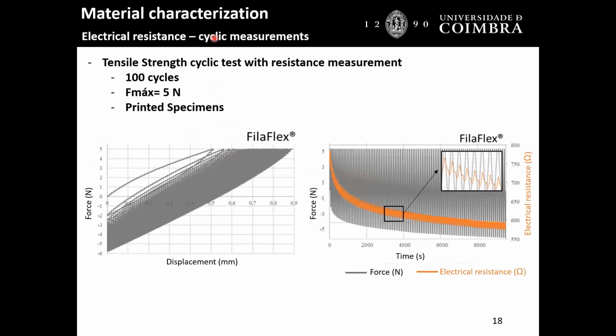And then we made, in the elastic deformation region, cyclic measurements, okay? With a maximum force of 5 newtons, 100 cycles, only in the printed specimens. As expected, due to the viscoelastic properties of the polymers, we have a permanent deformation. In Filaflex, TPU based, during the cycles you begin to have a very big percentage of permanent deformation of the printed specimen. But what is interesting is that the electric resistance begins to decrease during the cycles, which means that if we use these printed polymers in components that are subjected to mechanical solicitation, you don't have problems with the values of conductivity, because in fact they will increase during the test.